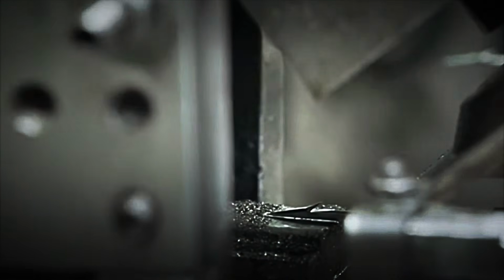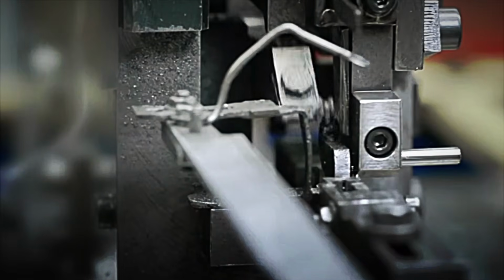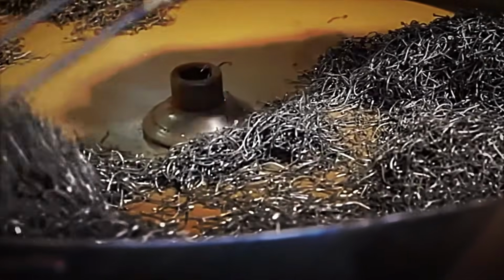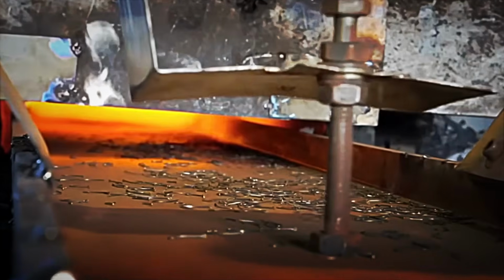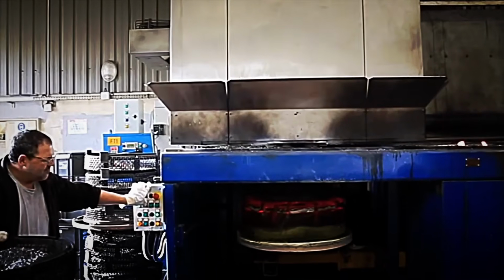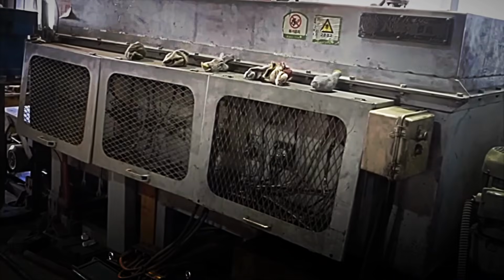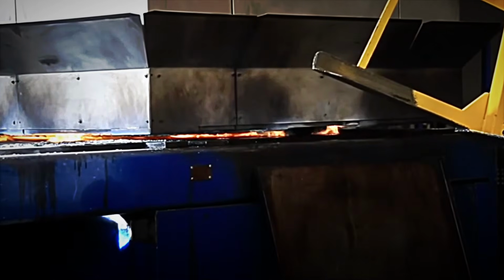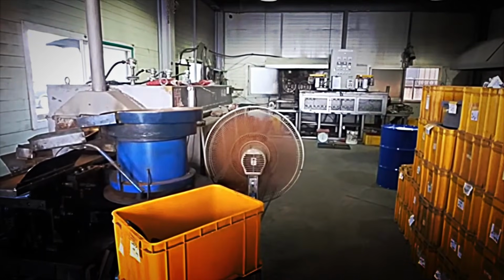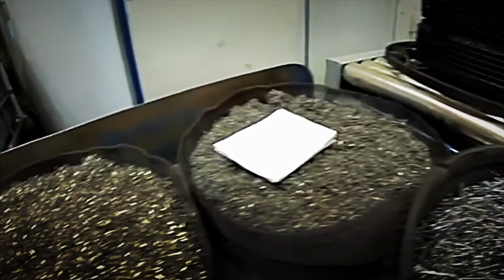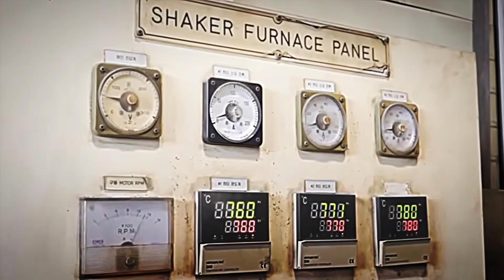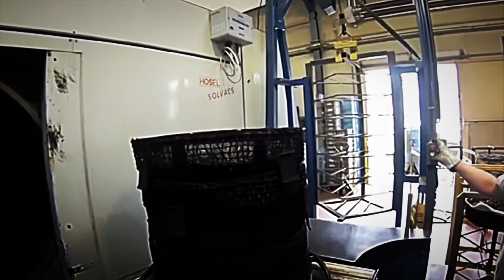They must undergo one of the most important processes in the entire manufacturing sequence: heat treatment. The hooks are placed on a metal conveyor belt that carries them into a continuous hardening oven. Inside, the temperature typically rises to approximately 760 to 870 degrees Celsius. At this thermal level, the steel's internal crystalline structure begins to transform, allowing the material to reorganize its microscopic composition. After reaching the appropriate temperature, the hooks are rapidly cooled in a controlled environment. This sudden cooling locks in the metal's new structure, significantly increasing its hardness.